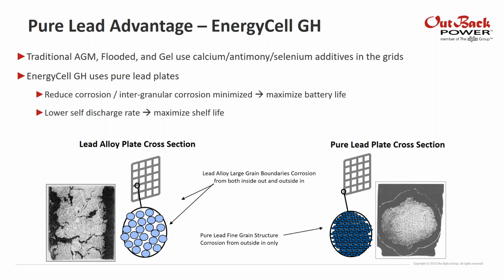And then if we think about this with a high temperature setting, so again, those large grain boundaries on the left-hand side with the lead alloy, in high temperature settings, those corrosion rates and the impurities are going to significantly increase the amount of corrosion that happens. Whereas with the pure lead plate, those impurities, again, aren't there. They're not able to contribute to the corrosion rate, so they don't. So that corrosion rate is not as high at higher temperatures as it is with a lead alloy plate.